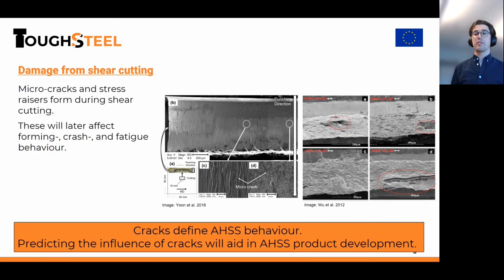A common conception is that the shear cutting process that you find early in the production stages induces damage in terms of micro cracks. These cracks will later on affect all of the processes previously mentioned, because these cracks will grow during forming of the sheared edges, and they can turn into edge cracks. During a crash, we have extreme deformations. These micro cracks are likely to be stretched and propagated, and in the worst case, this can impair the performance of your crash-absorbing part. And fatigue cracks can, of course, also grow from the micro cracks and become an initiation for fatigue failure.